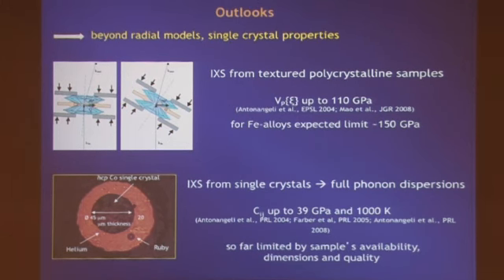In the case of iron, the big problem was the lack of availability of iron in the hcp phase as a single crystal. But one trick we can play is to press the sample without pressure transmitting medium, forcing uniaxial stress and developing preferential orientation of the c-axis of the hexagonal crystal along the main compression axis of the cell, so that, playing with the cell geometry, we can probe different directions. Doing this exercise, we get up to 3% seismic sound velocity difference, so the order of the seismic anisotropy. However, this kind of approach has an intrinsic limit in the pressure you can achieve, because as soon as the phonon of iron reaches the one of diamond, the more intense phonon of diamond will stop that.